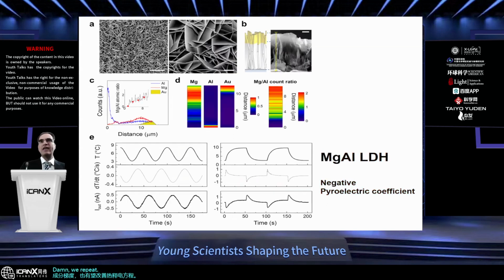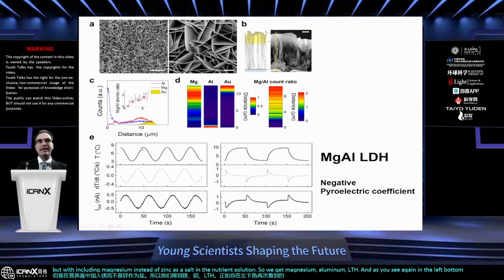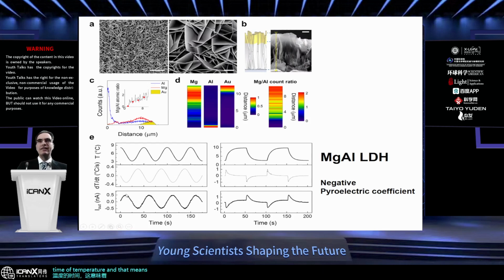Then we replicate exactly the same experiment, but including magnesium instead of zinc as a salt in the nutrient solution. So we get magnesium aluminum LDH, and as you see, again in the left bottom figures, you see the sinusoidal temperature variation and the derivative of temperature with respect to time, but this time the output current is the opposite of the derivative with respect to time of temperature. And that means that the pyroelectric coefficient now is negative. So by just changing the divalent cation, we can change the pyroelectric coefficient from positive to negative.